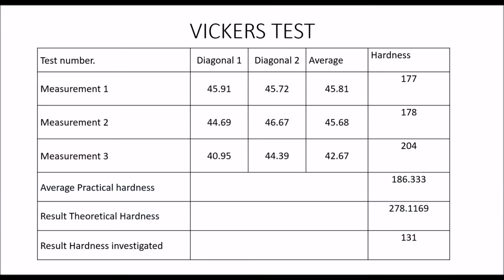The last hardness test that we made was the Vickers test. We made this test using the bakelite with the specimen of steel 1018. This specimen was cut out from the probe that I used in the tensile test, and we have 3 measurements with the average of each measurement and the hardness of each one. In the first one we have 177. In the second one we have 178, and in the third one I got 204.